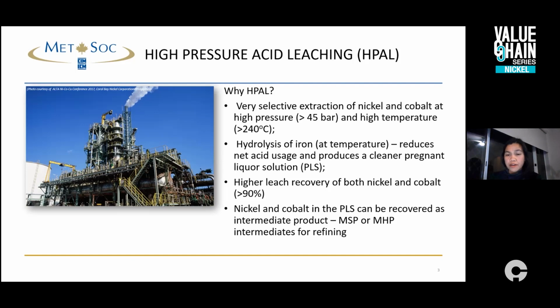And of course, at higher pressure and temperature, the kinetics of the leaching is faster, which is why nickel and cobalt recovery are in excess of 90%. From that pregnant liquor solution, which contains the nickel and cobalt, nickel and cobalt can be recovered downstream as an intermediate product, either as a mixed sulfide product or mixed hydroxide product.